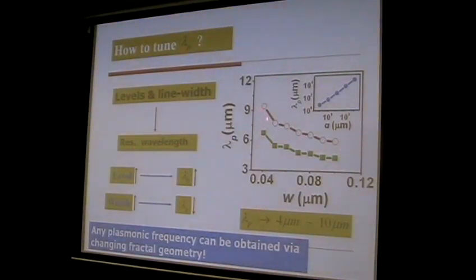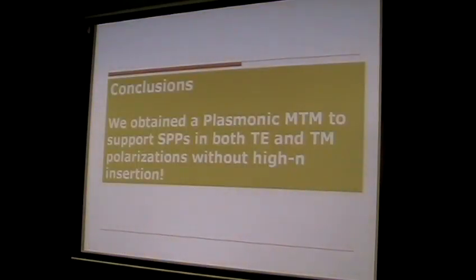This is shown here. We just change the line width of the fractal structure and can already have a very wide tunability. And also, if you scale down the whole size of the fractal structure, you can have resonance from microwave to far infrared very easily. So the conclusion is that we have obtained a plasmonics material based on fractal geometry to support the surface plasmons in both TE and TM polarization without high index material insertions.